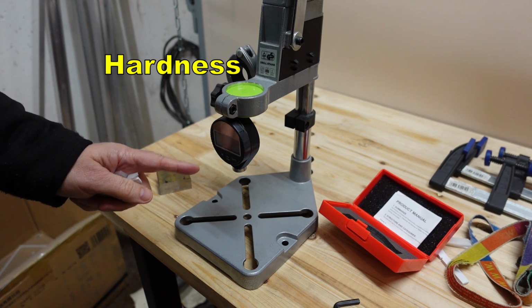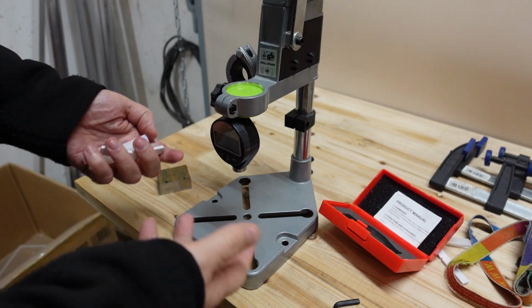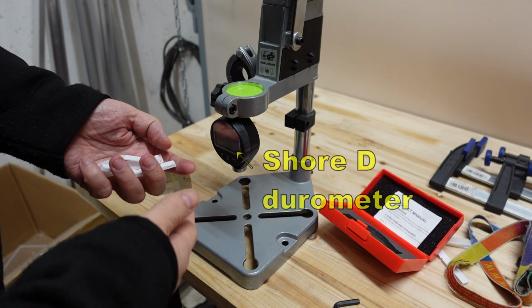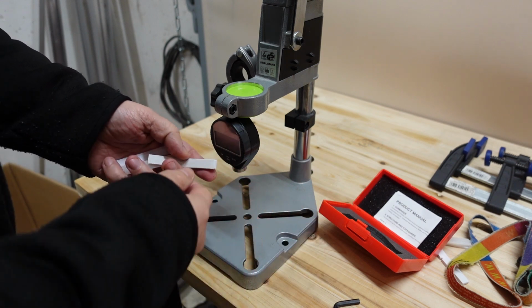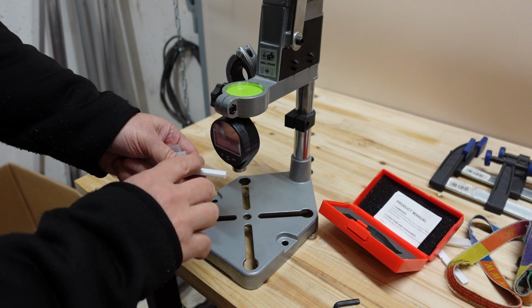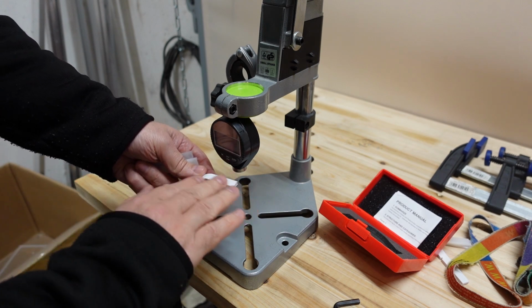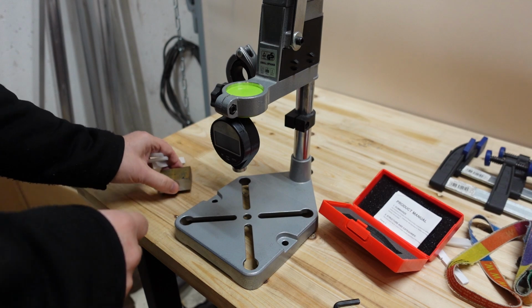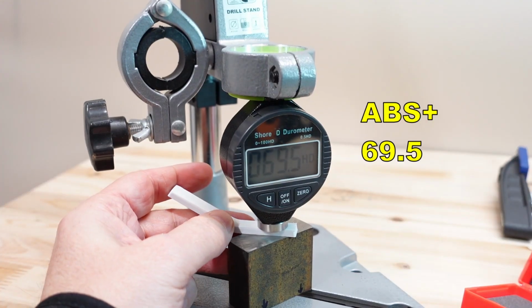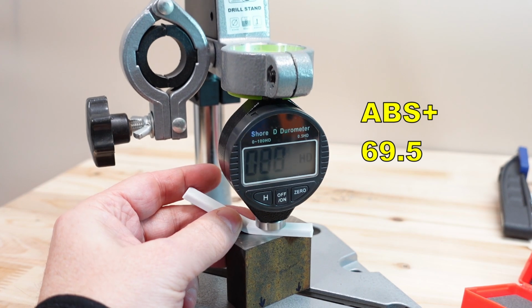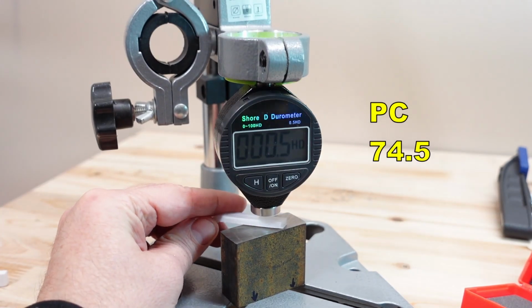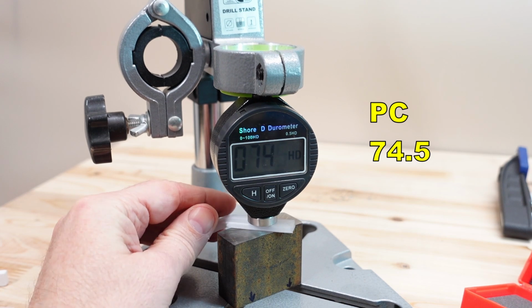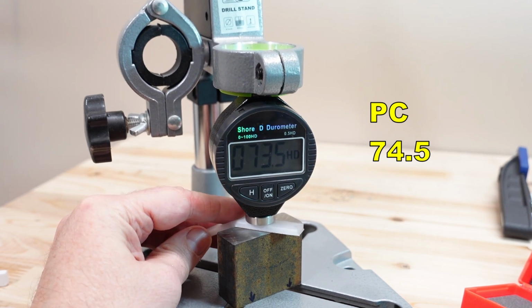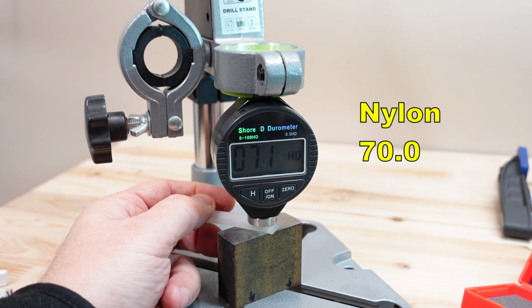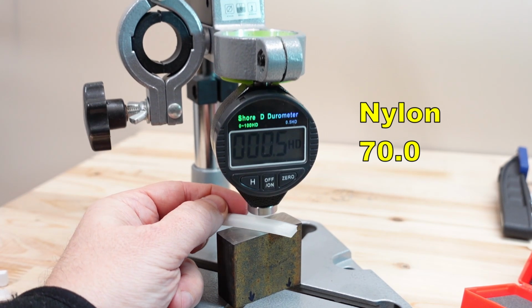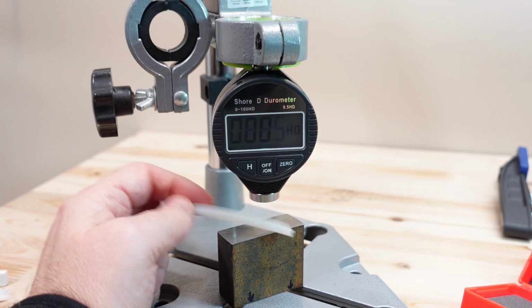I will measure the hardness with this Shore D durometer, and knowing the hardness, maybe we can know how scratch resistant some material is or something like that. And I will measure all these bending test specimens perpendicular to the layer direction. 69, 69.5, polycarbonate, 74.5. Smaller values mean softer material, and here I also noticed creeping of the nylon because it needed approximately 3 seconds to stabilize the penetration of the needle.